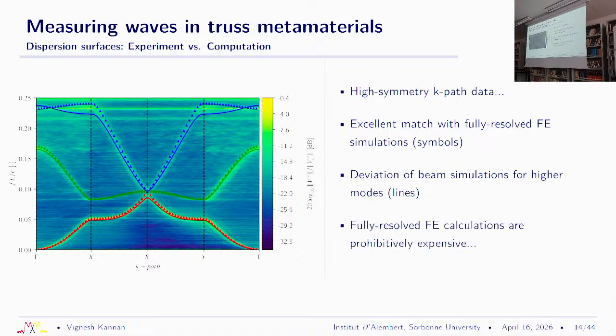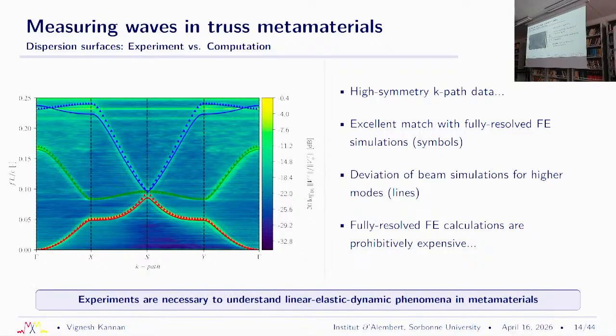So it turns out that yes, the experiments are useful, because then one of the questions would be, why do we even need the experiments if finite elements is doing a great job? One is 3D finite elements is expensive, and 2 is we were expecting at least that the Timoshenko beams were doing a good job, but it turns out they do not do a good job when you go to much higher modes.